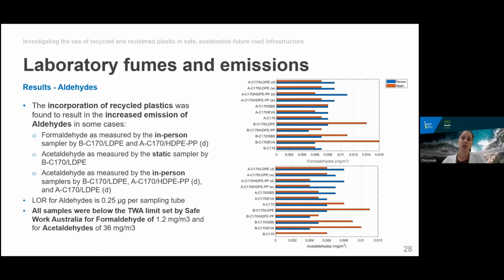In some cases, the emission of aldehydes, specifically formaldehydes and acetaldehydes, from the samples containing recycled plastics exceeded those of conventional materials. In all cases, however, those were found to be below the limit set by Safe Work Australia. The greatest concentration of formaldehydes was emitted by the EVA modified binder as measured by the static sampler, which was approximately 1.3% of the allowed limits, and for the acetaldehydes emitted by LDPE modified binder, which was at 0.03% of the allowable limits.